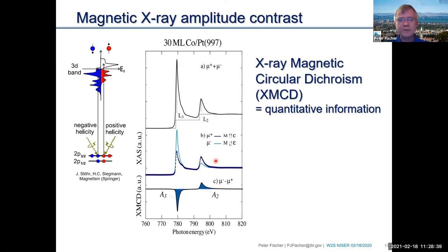Now, when you turn on the polarization, you see a difference in the absorption coefficient, and this depends on whether the magnetization of your system, the magnetic moments, are parallel or antiparallel to the helicity of the photons. And what you see here are two graphs. Again, this is the absorption profile as a function of photon energy for a specific element, in that case cobalt, and whether it's parallel or antiparallel, the helicity relative to the local magnetic moments, there's more or less absorption. That means you have a huge contrast. Look at the scale here, it's almost a factor of 2 for cobalt at this specific L3 edge, which means you should be able to distinguish between up and down, the spin pointing in the forward or backward direction of the X-rays.